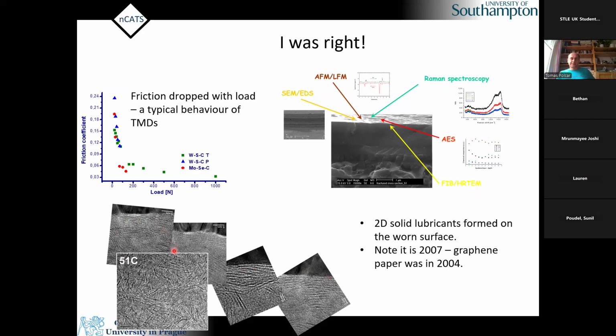And what we observed is this, and that's proof of this idea, which I had, that basically we form this very, very thin tribolayer. As you can see here, this is very high atomistic resolution. So you see rows of atoms, and these are actually 2D materials. It's similar to graphene. In this case it is molybdenum diselenide. It's another 2D material. But the important thing is that it was in 2007, and maybe you don't remember that, but the graphene paper appeared in 2004. So it was the very beginning when people started to speak about these 2D materials for completely different applications. And I was able to show them very nicely forming as a tribological process. So it was well advanced, I think, for the time, and I was quite proud of that.